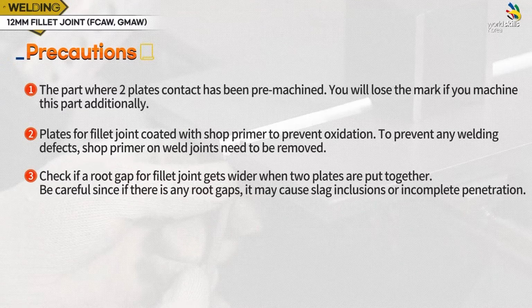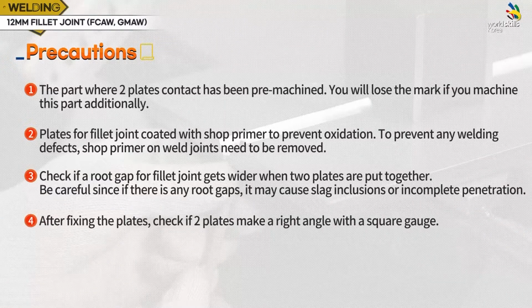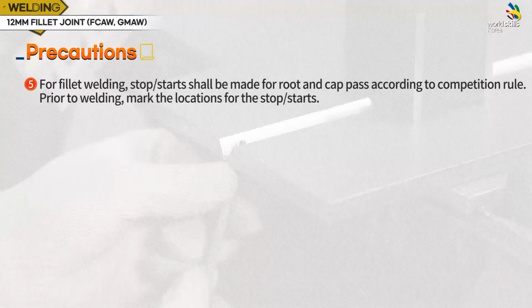Check if a root gap for fillet joint gets wider when two plates are put together. Be careful, since if there is any root gap, it may cause slag inclusions or incomplete penetration. After fixing the plates, check if two plates make a right angle with a square gauge. For fillet welding, stop-starts shall be made for root and cap pass according to competition rule. Prior to welding, mark the locations for the stop-starts.